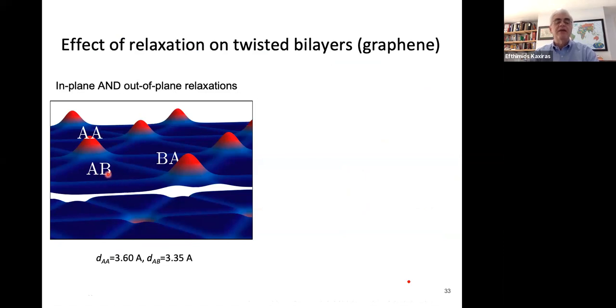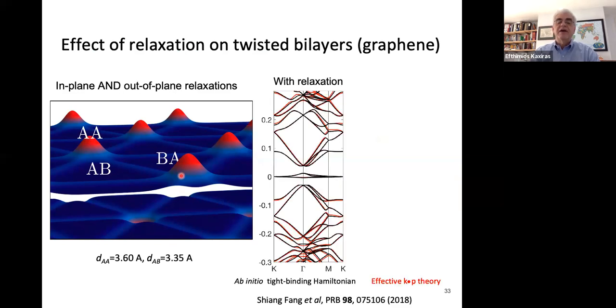So in a nutshell, this is what the atomic relaxation looks like, where you now see both the in-plane relaxation color-coded, as well as the out-of-plane relaxation. The atoms relax perpendicular to the plane as well. So here are the AA regions highlighted as red, with atoms moving away from each other in the two layers, and the AB or BA regions, which are the low-energy ones, where the atoms move closer to each other between the two layers. And related to this are very important effects on the band structure.